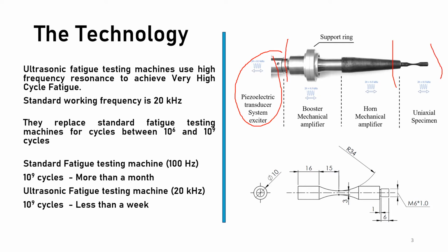It's only through this testing machine that we can reach 10 to the power of 9 cycles in a reliable time. If we compare this to a conventional standard fatigue testing machine, reaching such a high number of cycles can take easily more than 1 month, while ultrasonic fatigue testing machines can easily take less than a week.